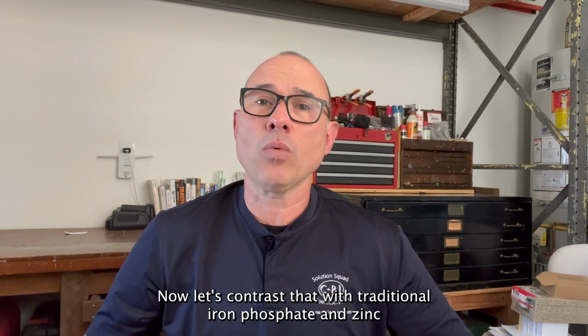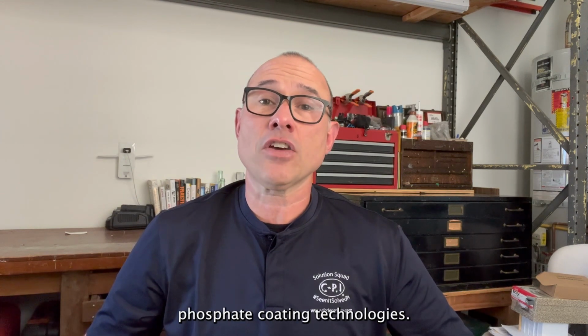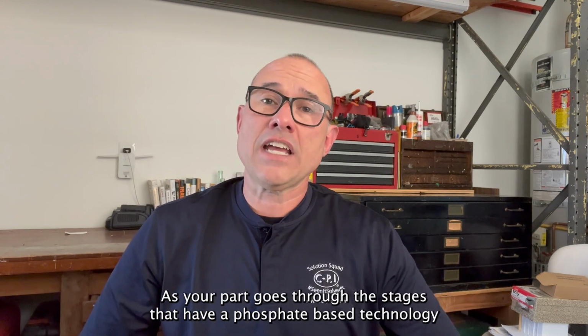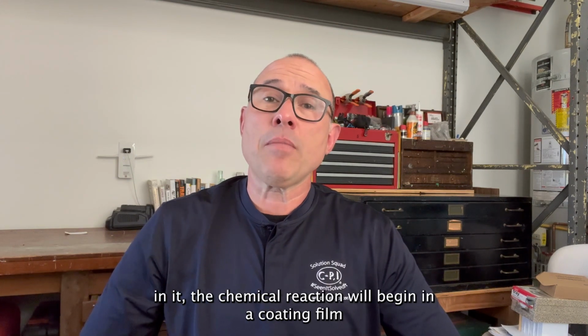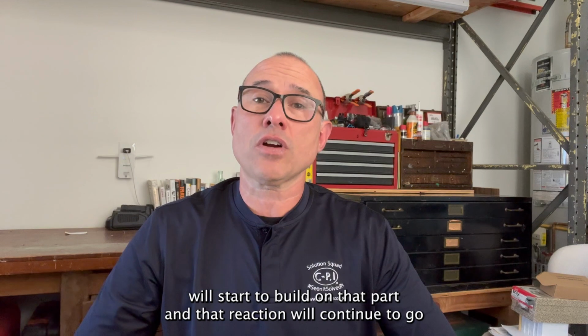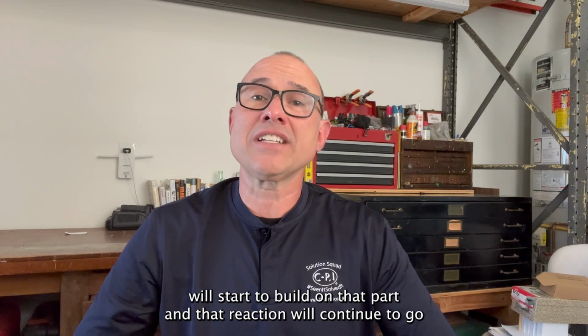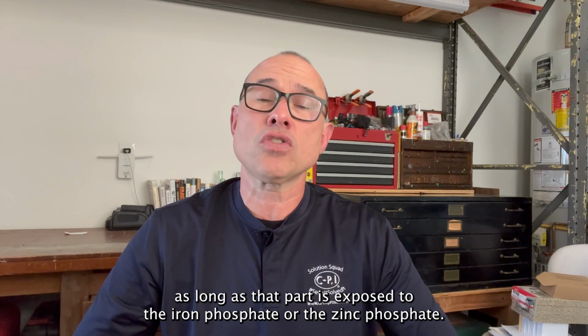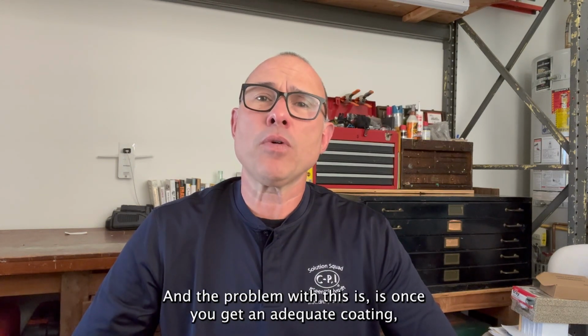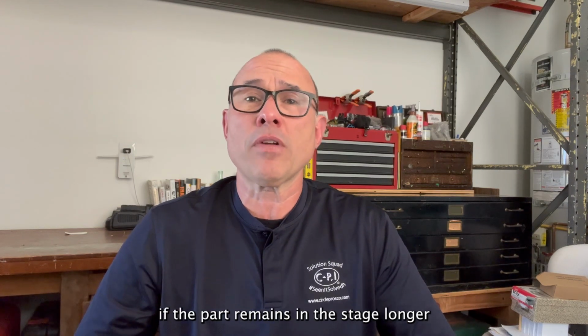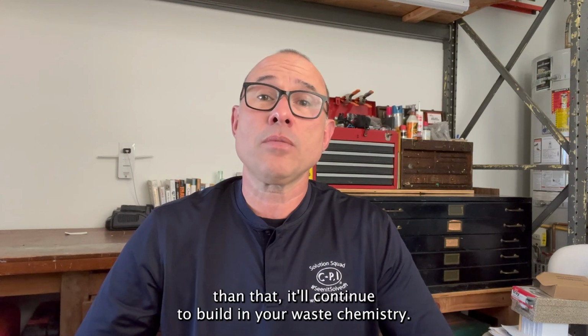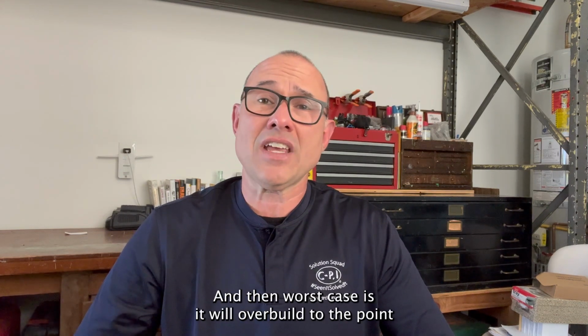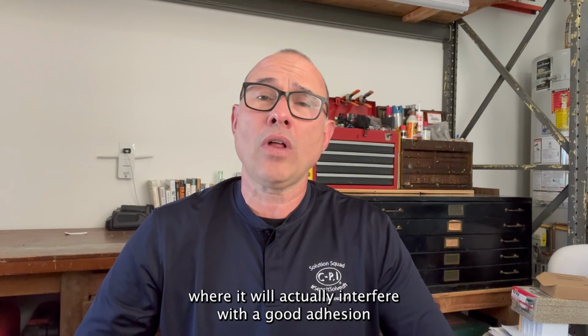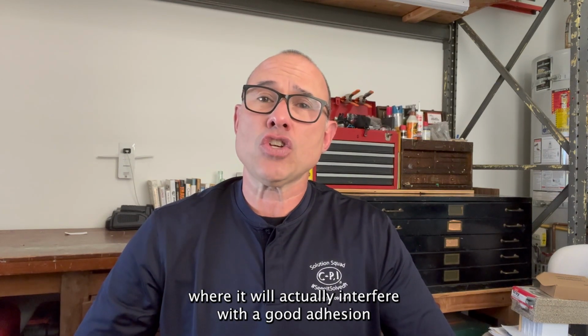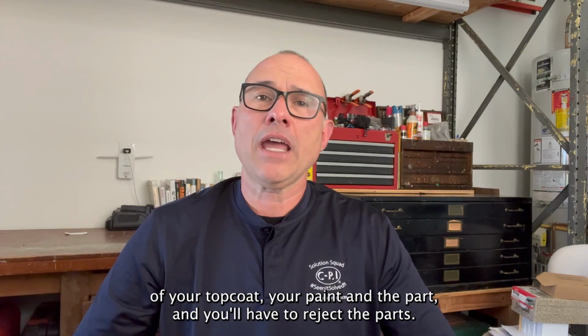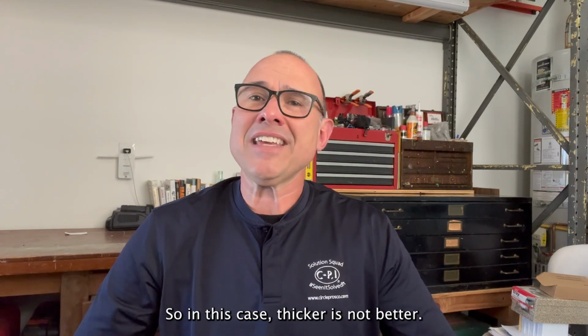Now let's contrast that with traditional iron phosphate and zinc phosphate coating technologies. As your part goes through the stages that have a phosphate-based technology in it, the chemical reaction will begin and a coating film will start to build on that part, and that reaction will continue to go as long as that part is exposed to the iron phosphate or the zinc phosphate. And the problem with this is once you get an adequate coating, if the part remains in the stage longer than that, it'll continue to build and you'll waste chemistry, and then worst case is it will overbuild to the point where it will actually interfere with a good adhesion of your top coat, your paint, and the part, and you'll have to reject the parts. So in this case, thicker is not better.